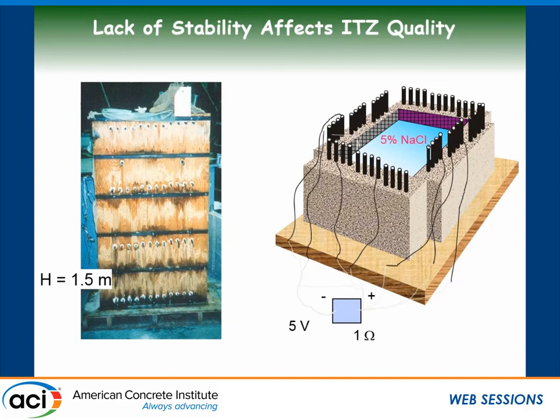In this study, we wanted to look at the effect of surface settlement of SCC stability on corrosion behavior of concrete. So we cast some wall elements, 1.5 meters, and we have a set of rebars, as you can see over here, kind of staggered, and then we saw cut those into four different sections. We connected them together, and we did some accelerated corrosion testing. So we're looking at the onset of corrosion between the cathode and the anode, which is the rebars, for rebars having different covers.